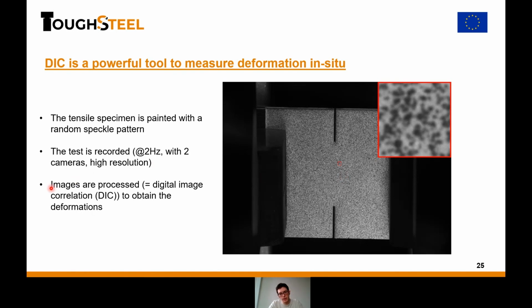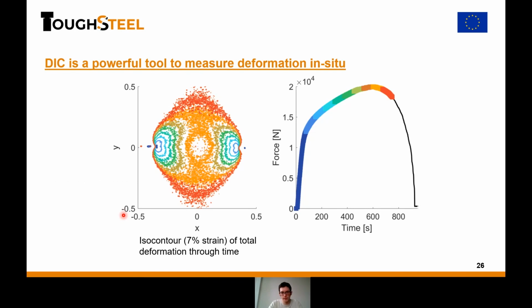And then after the test, you process all the images and you compare each pixel between each image. And so that way you can obtain the deformation through time. And so this allows me to draw this type of graph. So it's quite a lot of information on one graph, so I will try to take a bit of time to explain it. What is drawn on the left is the isocontour on your DENT specimen. In this case, it's a 7% strain isocontour of the total deformation at a point in time. So here you can see, well, you can guess where the notches were on my DENT specimen.